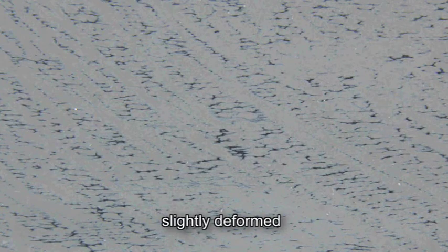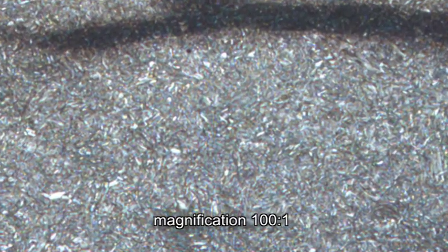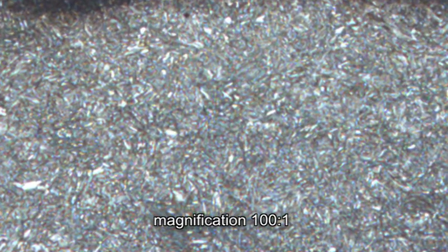Gas pores, as well as shrinkage cavities, are collapsed and their inner walls welded together. Impurities and inclusions such as slag and non-metallic precipitations are broken up, reduced in size, and dispersed. This neutralizes any negative impact on the mechanical properties of the forged part. In the case of steels, there is a special effect. Hot forging leads to full-scale recrystallization, i.e., the transition from old crystals to new, very small crystallites that can only be seen at high magnification. In combination with sustainable heat treatment, this can be used to significantly improve strength and toughness.